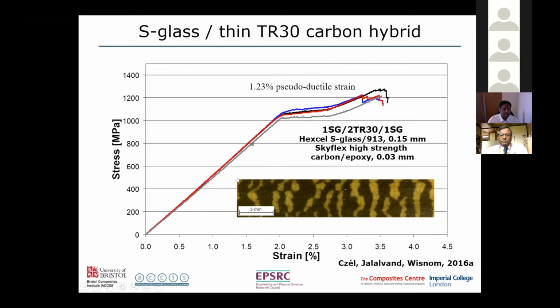So, showing the results for that combination of S-glass and thin, high-strength carbon. In this case here, we've used 2 layers of 0.03 millimeter carbon. So we've got 0.06 millimeters of carbon sandwiched between standard thickness S-glass. And you see we have this very nice plateau on the stress-strain curve. And in this particular case, we get about 1.2% additional pseudo-ductile strain beyond the point at which the carbon fibers start to fail.